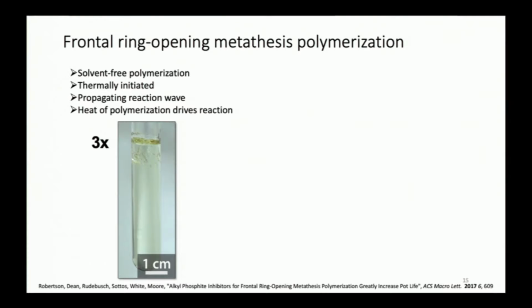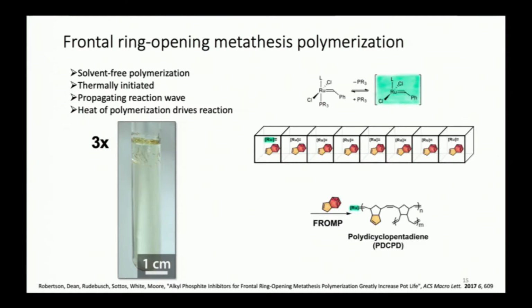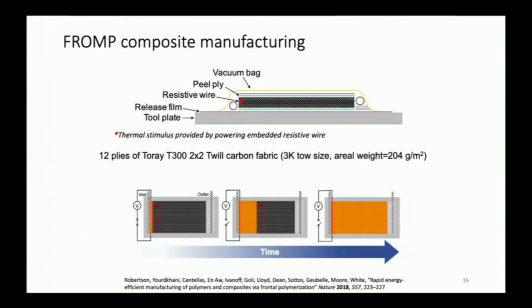But here, we're in this bulk polymerization using all of the energy, except for that very initial tap that you saw at the beginning, to that all of that energy comes from the initial event of initiating that reaction. It's the heat of polymerization that drives that. So there's the chemistry. There's an activation step. That's what happened at the very beginning. And then heat transfers to the adjacent area, and then the process continues over and over again. And so the only energy input is that which gets this process going from the very beginning.